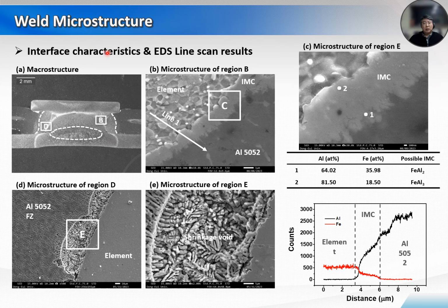Because resistant element welding is a dissimilar material joint, the formation of intermetallic compound, which deteriorates the property of the weld zone, actually occurs. Therefore, to analyze the intermetallic compound development, EDS line analysis was performed on the intermetallic compound part formed between the element and aluminum. About a 2.5 micrometer layer of intermetallic compound has developed. However, we found that it did not affect the quality of the fastening in the applied welding parameters. However, with excessive heat input, this may cause degradation of the joint due to very large intermetallic compound formation.